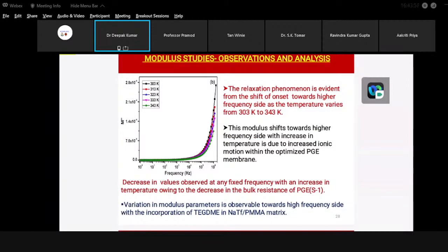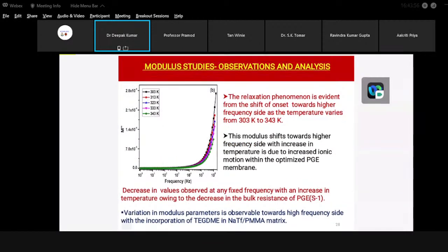And as a function of temperature also, we have investigated this electrolyte system, the optimized one, and we see that there is a small shift, which is again indicating that the electrolytes are very good, and in a wide temperature range the overall feature of the electrolyte does not change. However, a small change is there in the relaxation peak, which is indicating the change in the relaxation time and further change in various parameters like mobility and charge carrier concentration and so on.